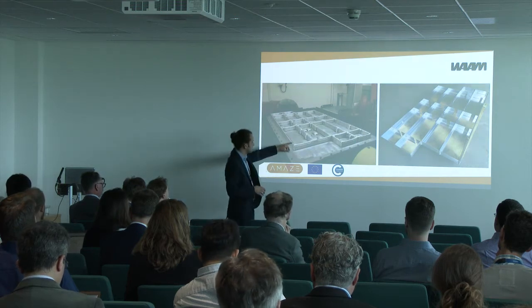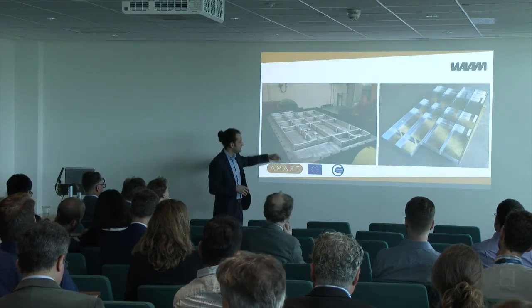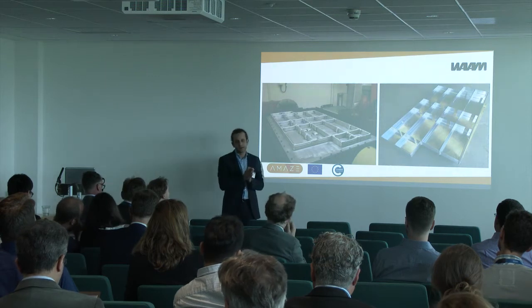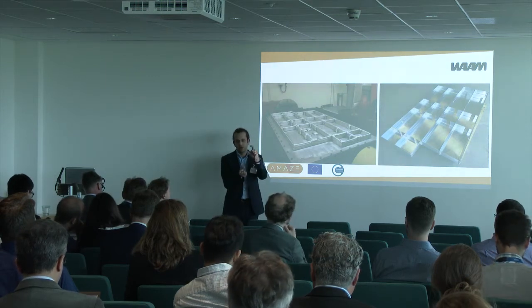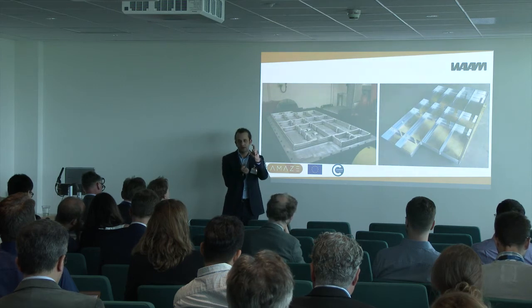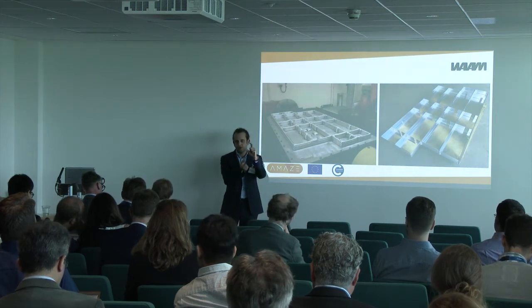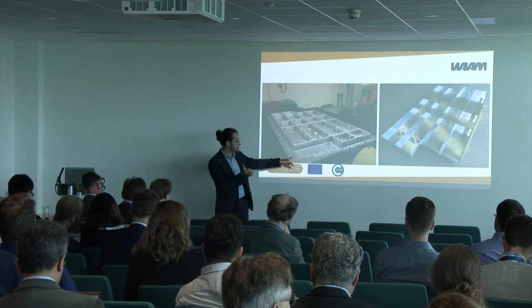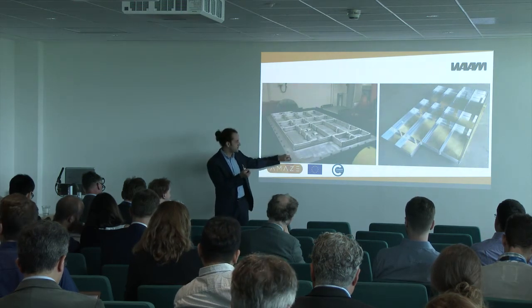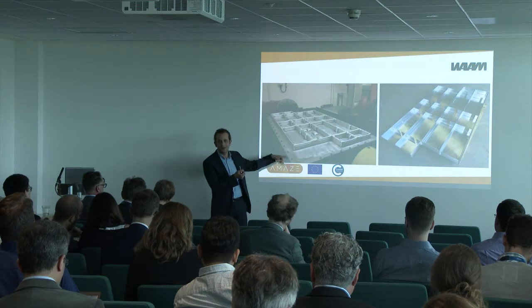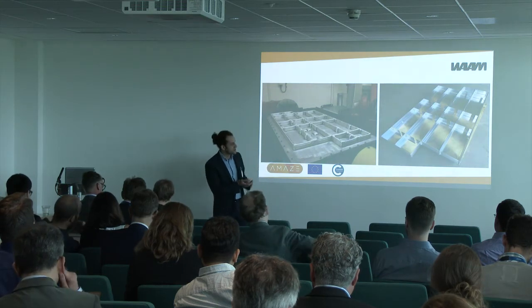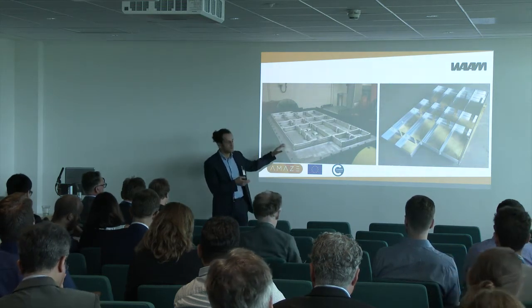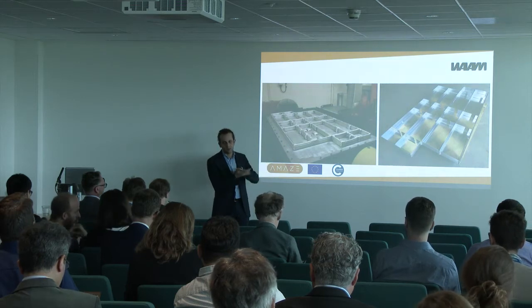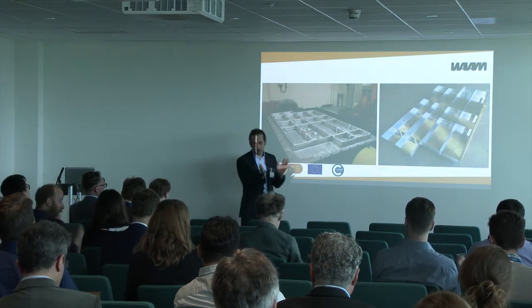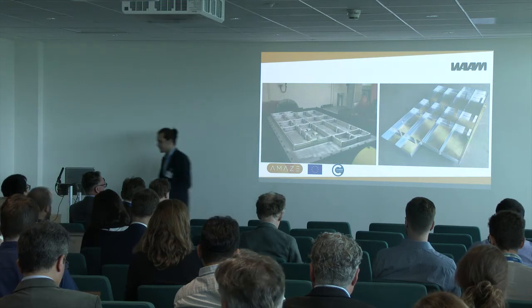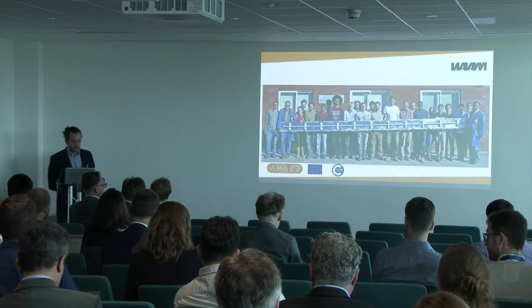So in this case, there is an identical part on the opposite side of the plate, and that is to balance the residual stress. Each of the 2 halves of the component will have identical residual stress in magnitude, but the direction is the opposite, and therefore the net effect seen by the base plate is 0, which means that the part will have no distortion when you unclamp it. What you see on the right-hand side is only one of the 2 halves. So after building, you heat treat, you split, and then you've got your 2 parts separated and without distortion.